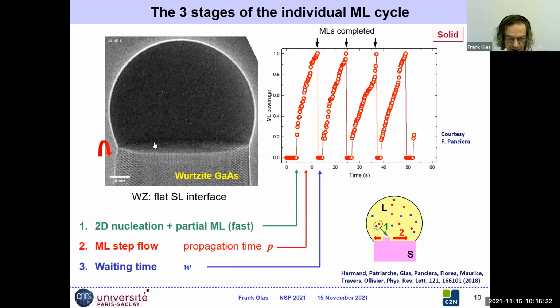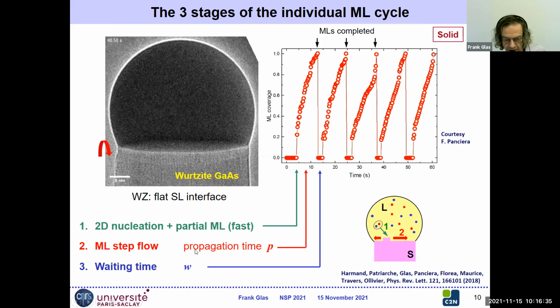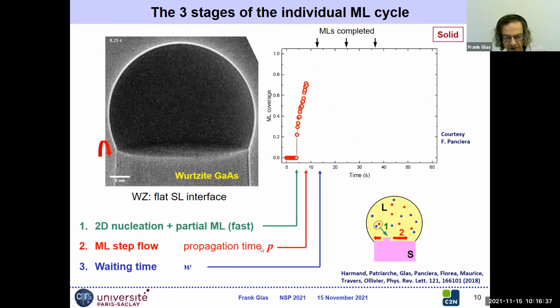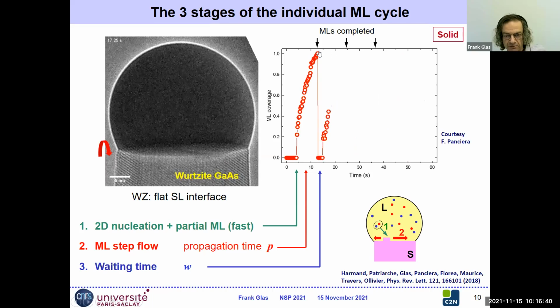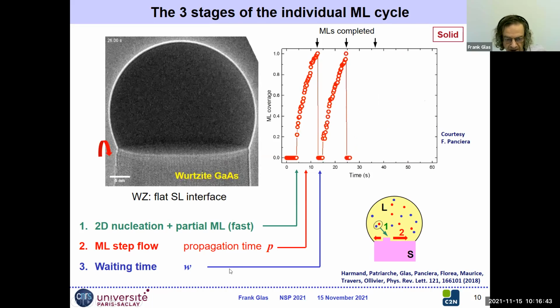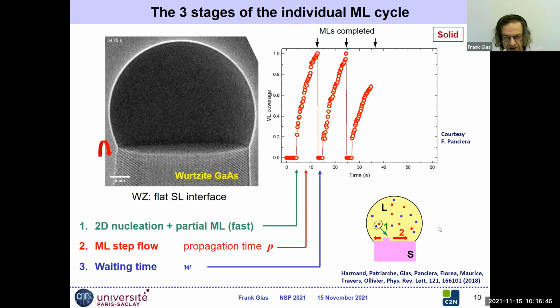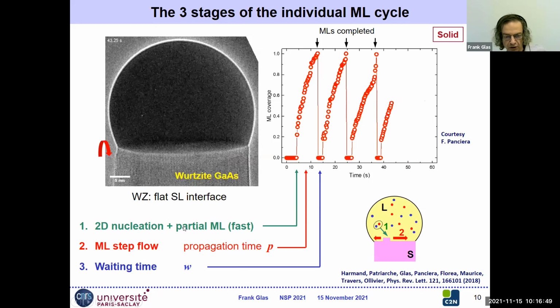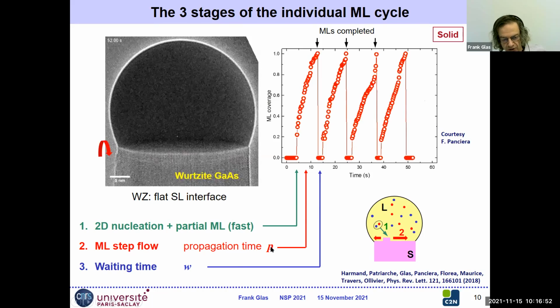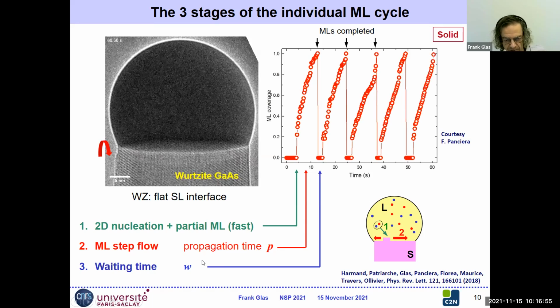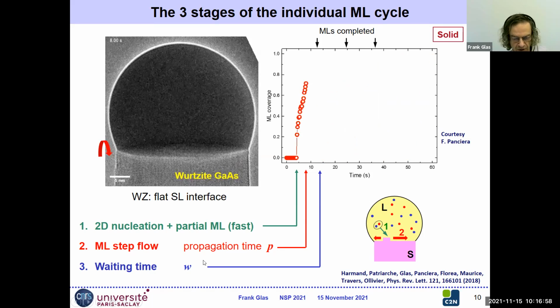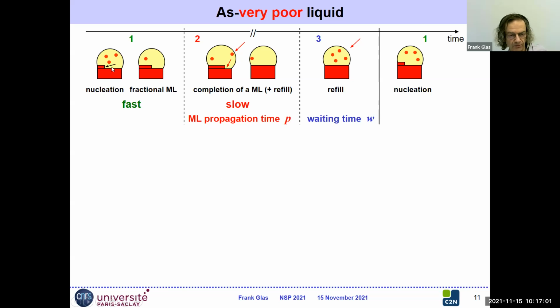The second stage that we can observe here is the step flow. So today I will call this the propagation time, P in red. And once the layer is propagated and completed, we have a waiting time here in blue, W. So 3 stages: nucleation, partial monolayer formation, propagation of the partial monolayer until completion, and waiting time where apparently nothing happens except that the vapor fluxes refill the droplet. So these are the 3 stages: nucleation, fractional monolayer, fast, completion of a monolayer and refill of the droplet, stage 2, slow, waiting time, stage 3, and then we start the cycle again.